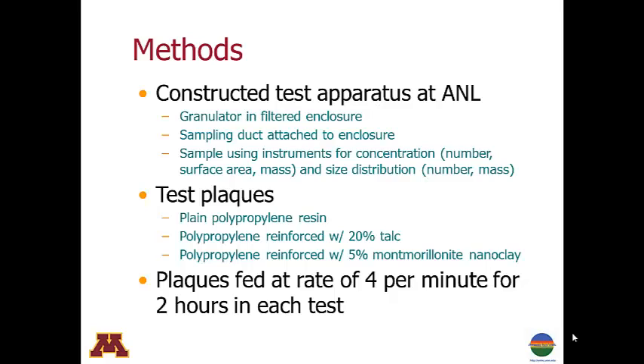We shredded small test plaques of three different polypropylene plastics: plain polypropylene resin, polypropylene resin reinforced with 20% talc by weight, which is a conventional composite plastic, and the nanocomposite, polypropylene resin reinforced with 5% by weight montmorillonite nanoclay. These test plaques were fed into the granulator at a rate of 4 per minute for 2 hours for each of the plastics.